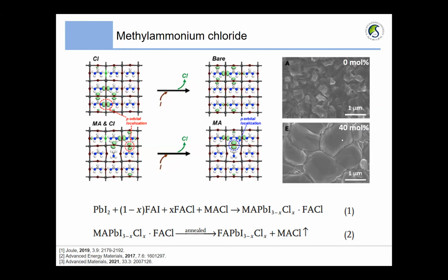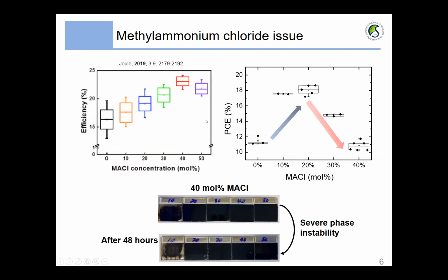And also, it can enlarge the grain size, which reduces the trap density. Actually, the trap density is highly correlated with the density of the grain boundaries. So MACl is a great candidate for additive engineering. We tried to fabricate the devices following the previously reported MACl studies. This is the box plot of the efficiency of the FAPbI3 solar cell according to the MACl concentration.